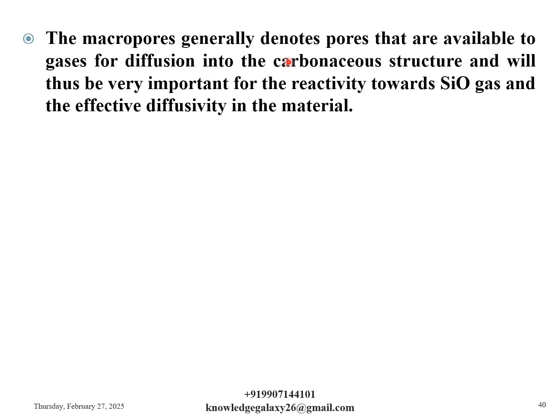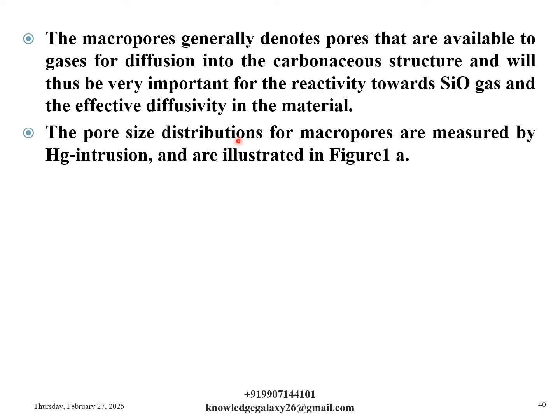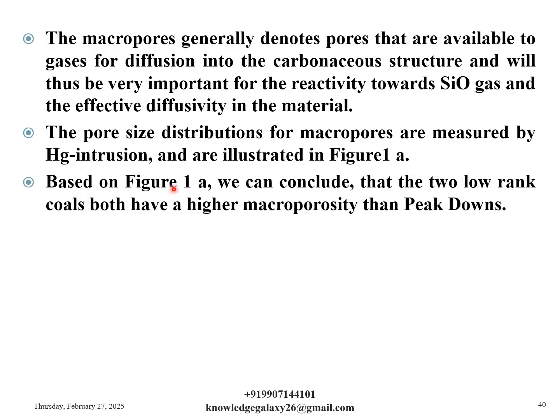The macropores generally denote pores that are available to gases for diffusion into the carbonaceous structure and will thus be very important for the reactivity towards SiO gas and the effective diffusivity in the material. The pore size distributions for macropores are measured by mercury intrusion and are illustrated in figure 1a, which is shown in the later slide. Based on figure 1a, we can conclude that the two low-ranked coals both have a higher macroporosity than Peak Downs.